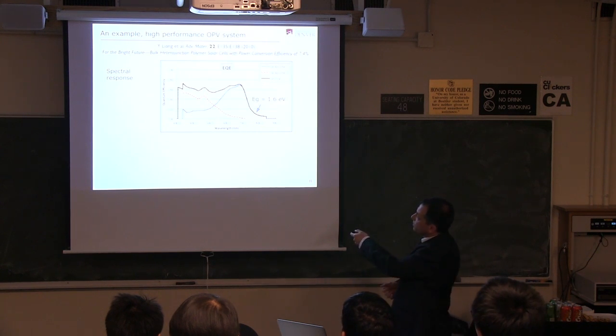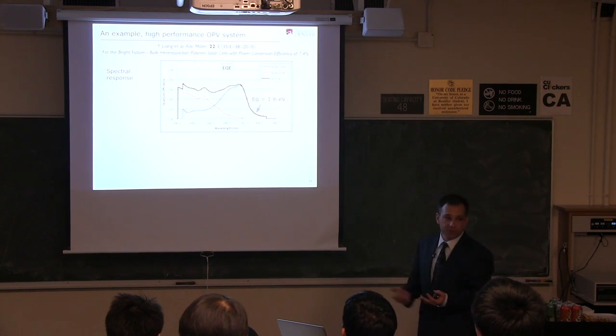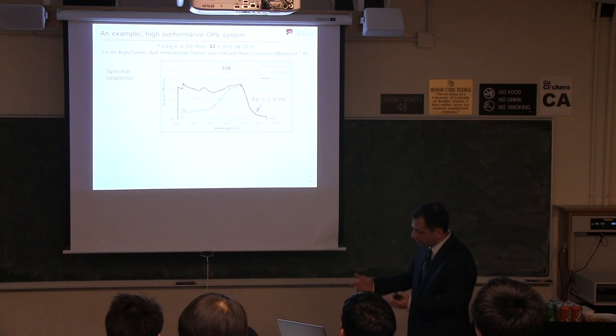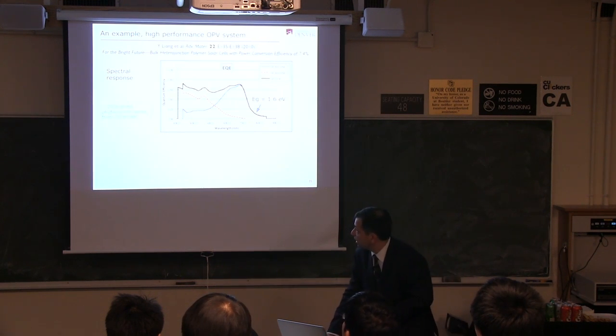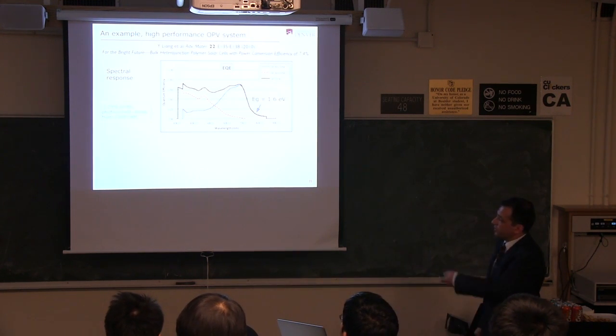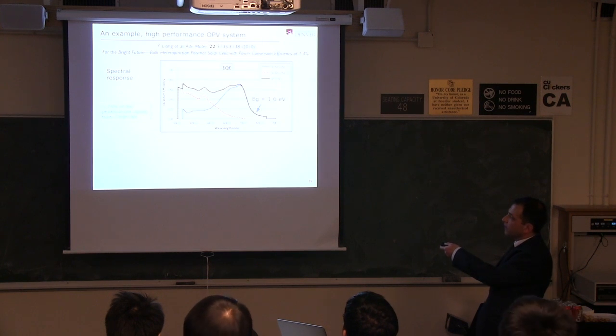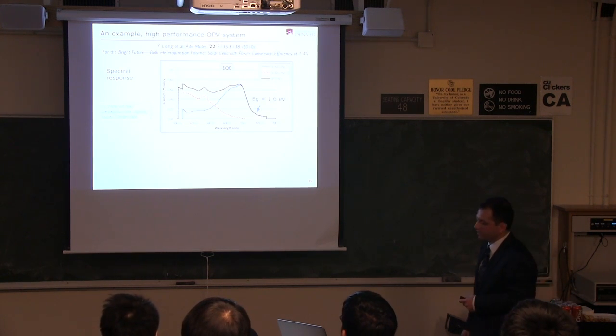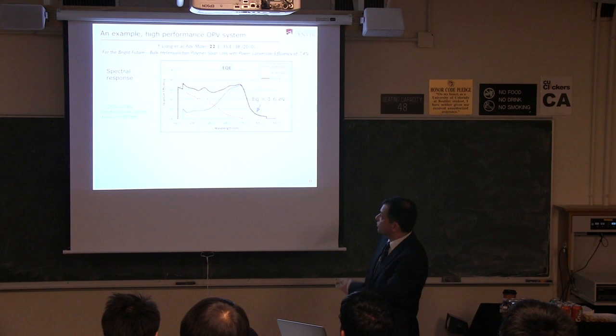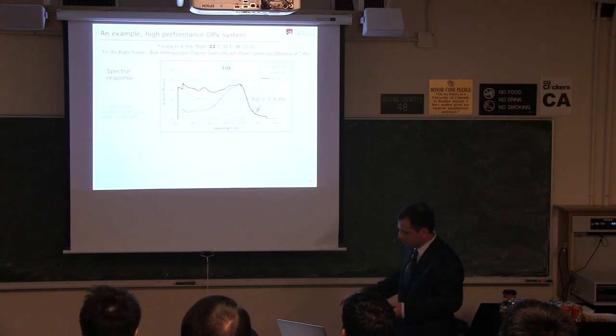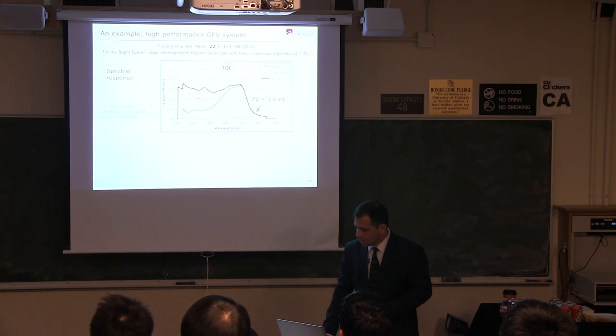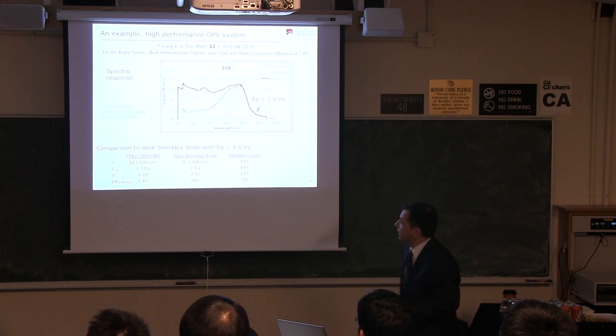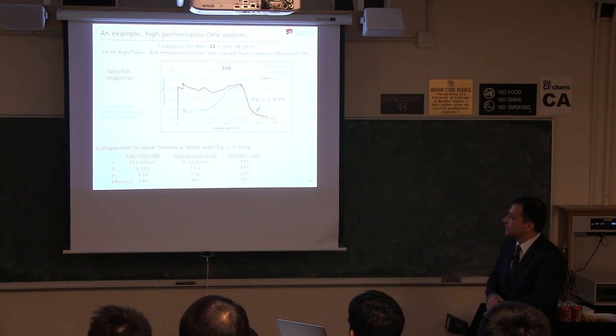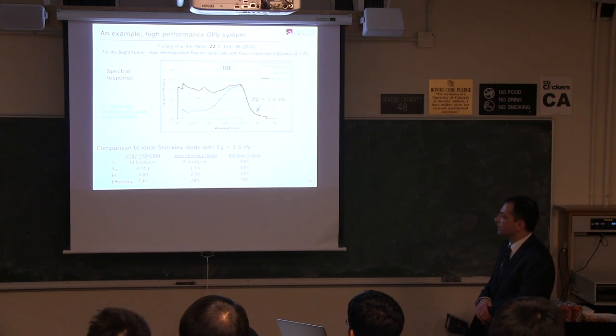The red curve here is the response of the fullerene, which does absorb some photons and produces a little bit of current. Overall, about a quarter of the current is coming from absorption of the fullerene as opposed to the polymer. So it's really important to have the fullerene in there, not only to extract charges from the polymer, but to produce current itself. So what I'll do is just do a comparison of an ideal diode, which would have a band gap of 1.6 electron volts, Shockley diode, to the numbers that we have here. Right?